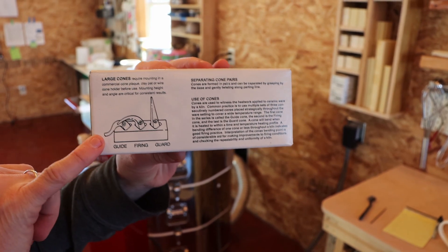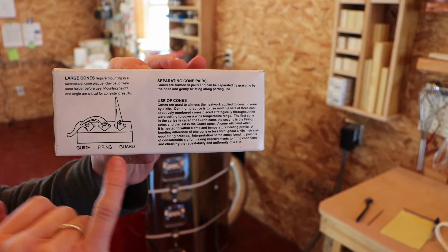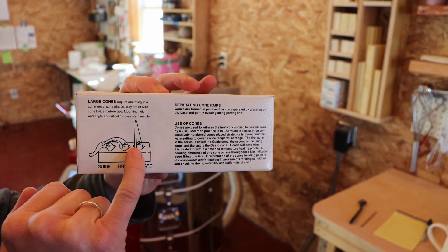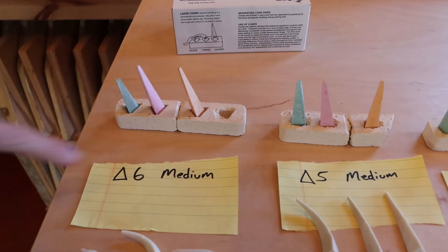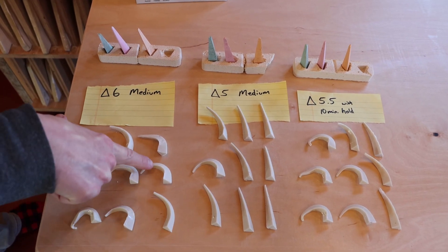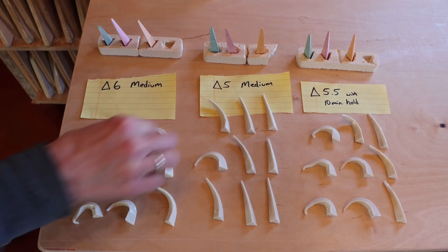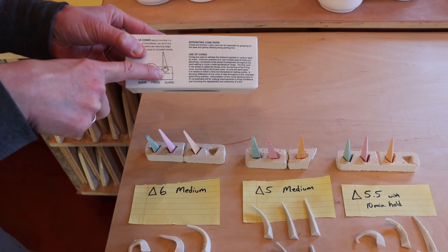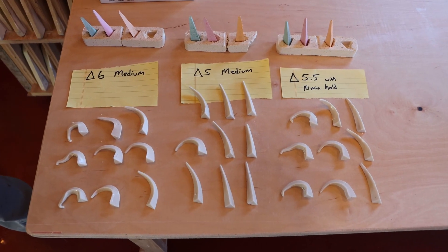The cone 5 should bend a lot, like the image shows. The cone 6 should bend at almost a curvy 90-degree angle. The guard cone, which is a cone 7, should remain straight or slightly bent. If it bends a lot, that shows it's way too hot. I've done many cone 6 firings and they've been getting progressively hotter. When I see the cone 7 guard cones bending quite a bit, that worries me. When the middle cone is all the way over touching and the guard cones are really starting to bend, that raised a red flag — so when we fired at a normal cone 6, it was way too hot.